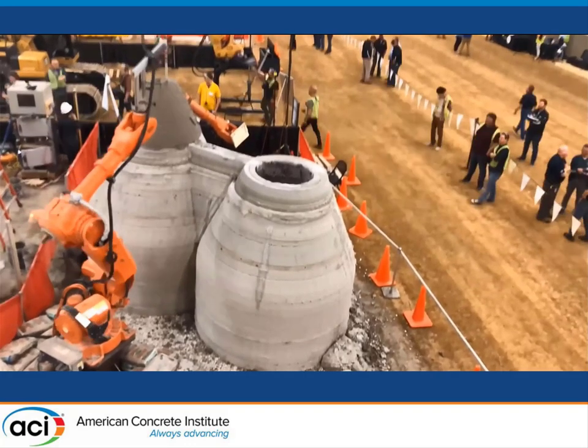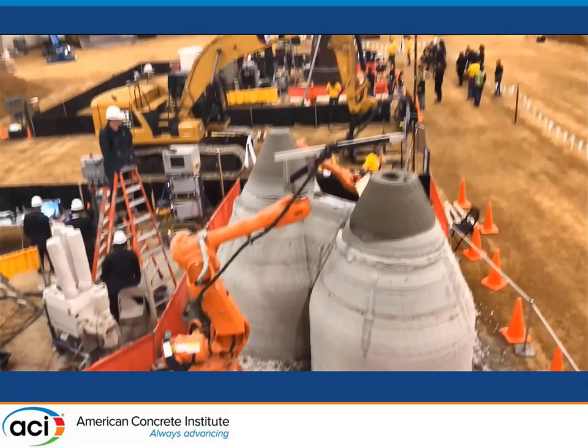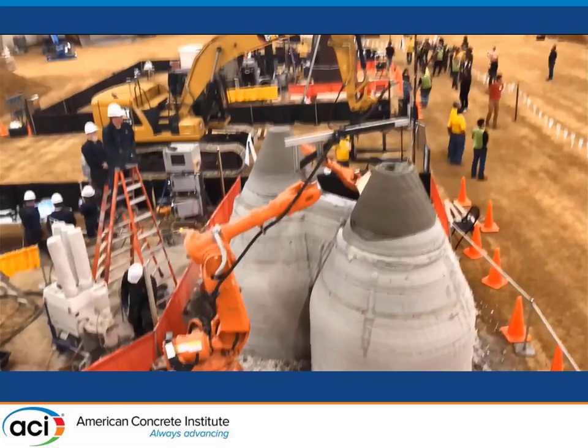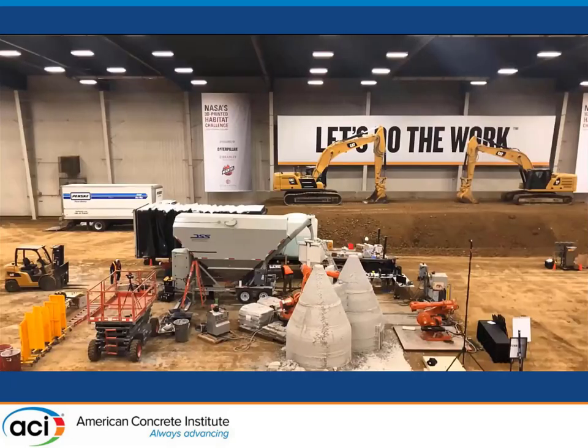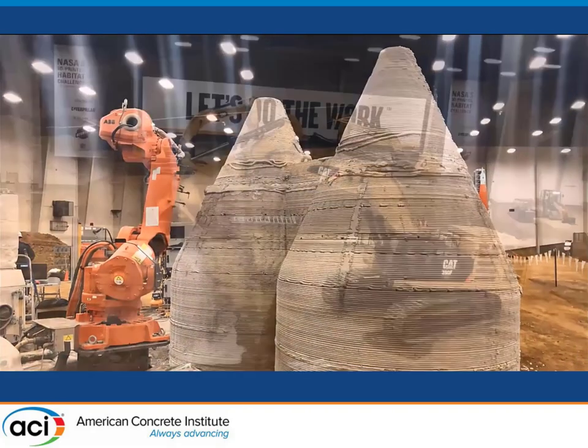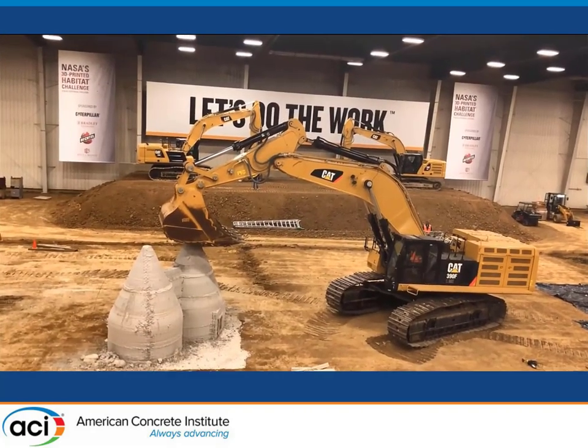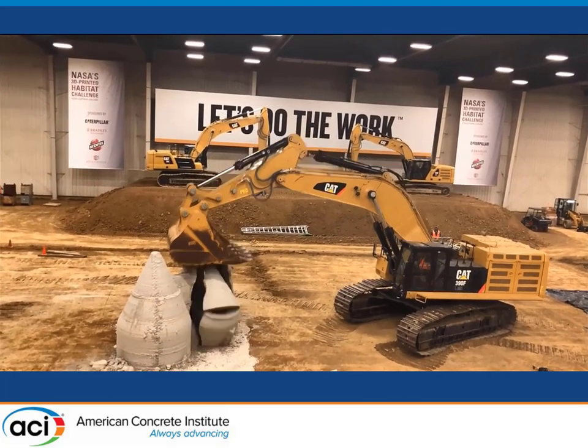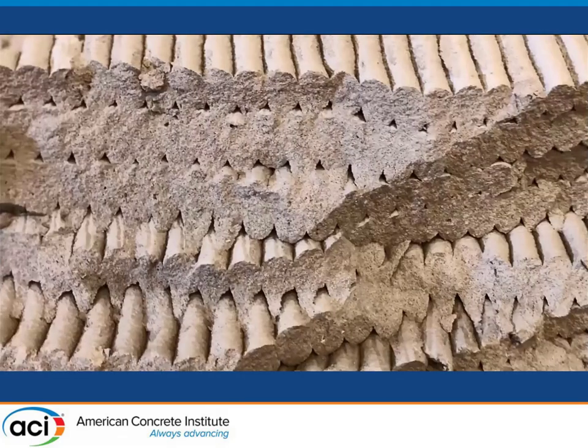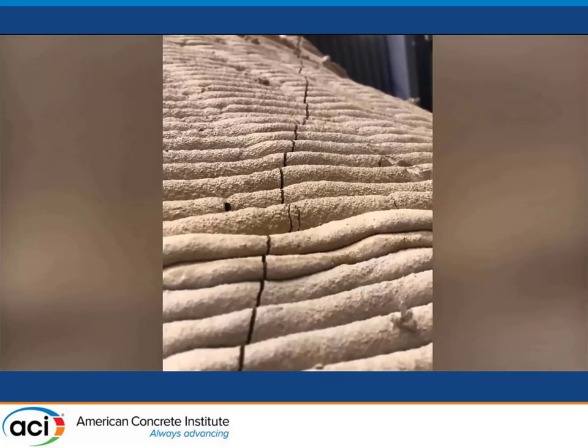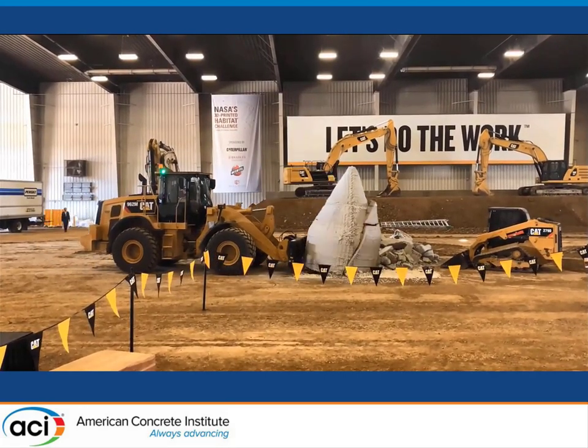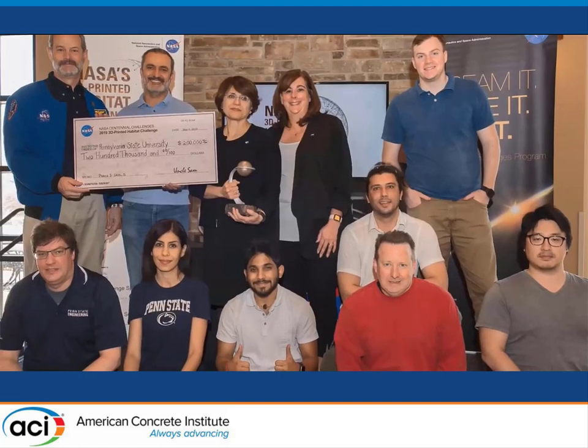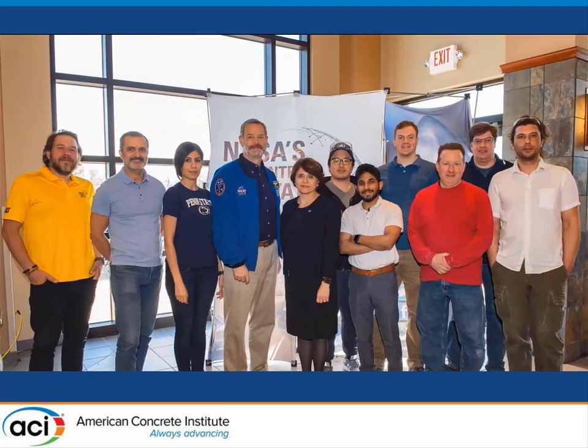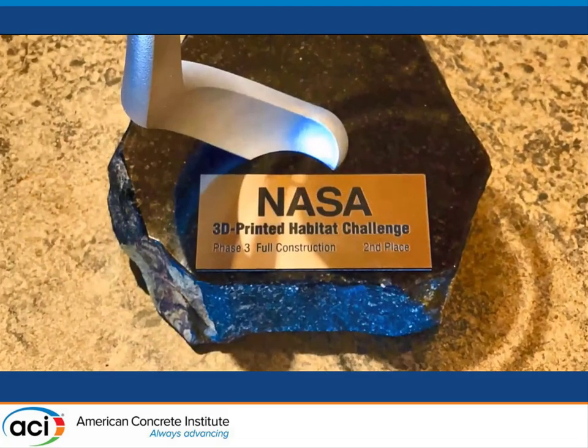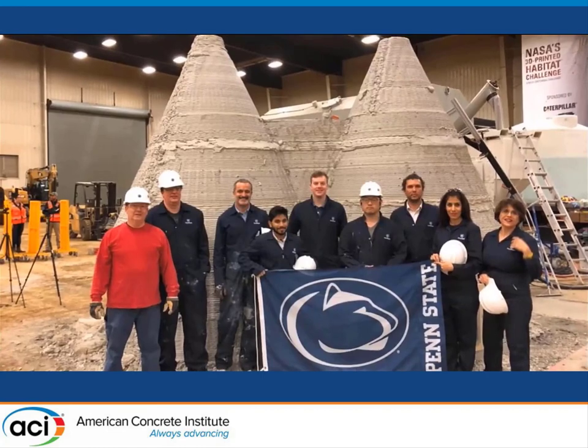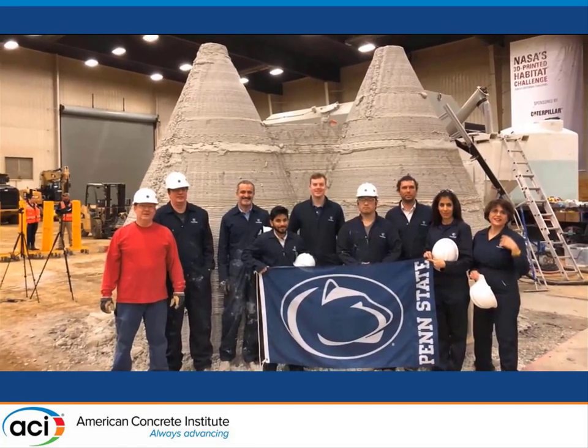You can see in the last part of this video that most of the failure happened because of the very weak joint between two layers. And here is where they did the crush test. After the crush test, we had the chance to take a look at what was going on. As you can see, the weakest part of the structure was the interlayer bond between two layers. So this is one of the questions that we need to answer, and we need to have more experience about that over time.